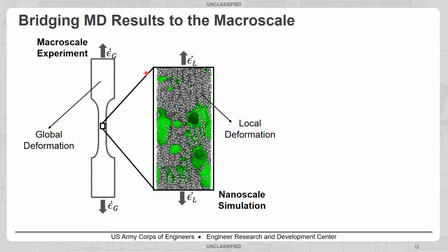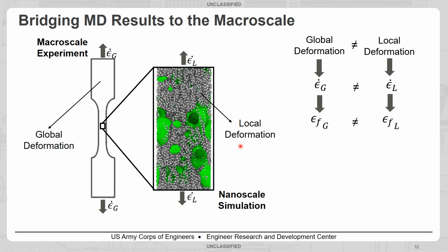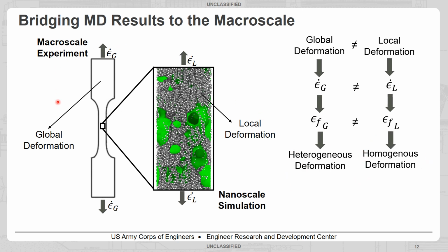So we have this macroscale experiment defined here, a global strain rate that leads to this global deformation behavior of this sample. We can look at a very small region, perhaps on the nanoscale, and then we can define here a local strain rate and a local deformation. The problem, as we see with MD simulations, is that the global deformation does not equal the local deformation. The global and local strain rates do not equal. The fracture strains are not equal. All of this because the macroscale experiment is heterogeneous in nature, while the nanoscale simulation is homogeneous in nature. So for the macroscale experiment, during deformation, certain heterogeneities, whether they be voids or particles or even just high triaxiality regions, will experience higher levels of strain rates and higher levels of deformation than what the macroscale experiment would.